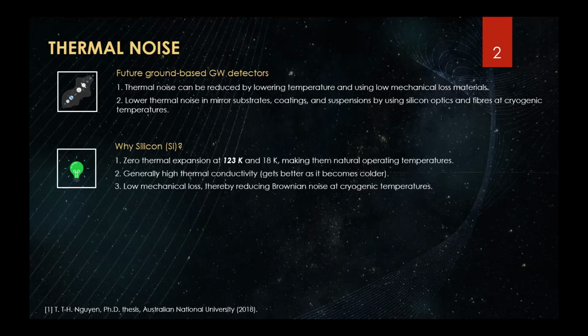And silicon is a strong substrate and a strong candidate for future detectors for the following reasons: because it has zero thermal expansion at 123 Kelvin and 18 Kelvin. So your thermoelastic noise in your substrate vanishes. It has high thermal conductivity and it gets better as it goes colder. Also, it has low mechanical loss, which reduces the Brownian noise at cryogenic temperatures.